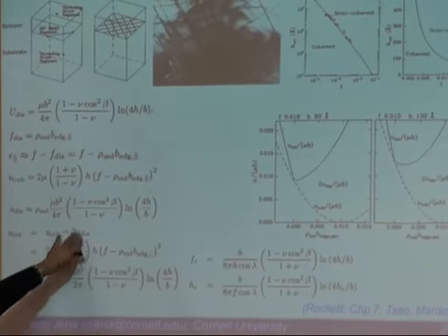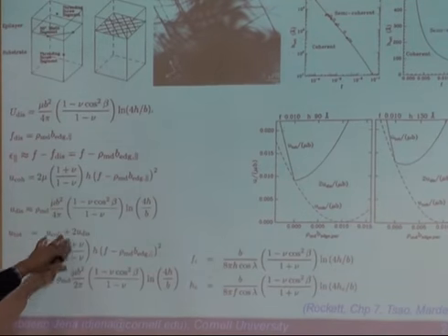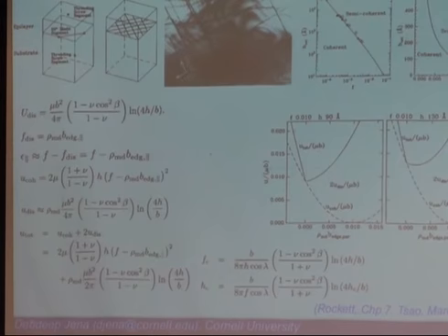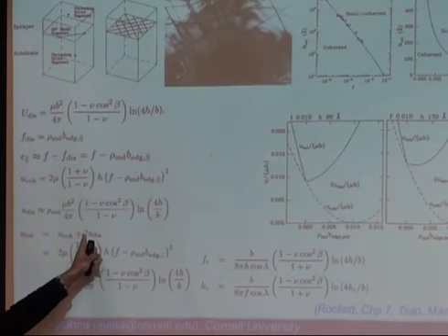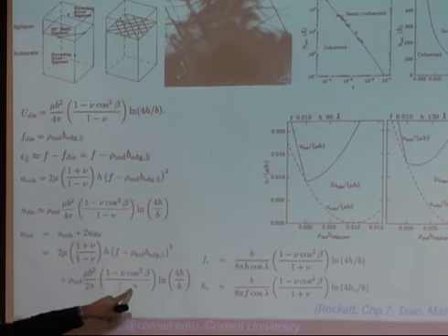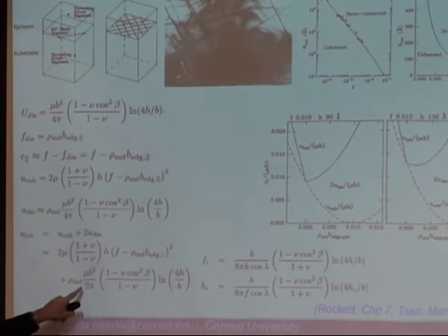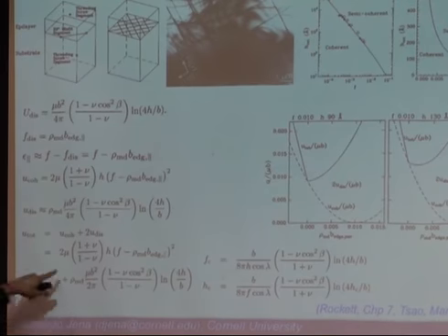Okay, let me just say, there are twos, and all these one can explain very clearly. The two comes about because the picture we're looking at now is if it had, for example, a dislocation in this direction and a dislocation in that direction, x and y. So there's a spacing along x, there's a spacing along y, right? So you form these dislocations, so there are two axes along which dislocations are formed. Just like we're summing it for epsilon along x, epsilon along y. Same thing here. You sum the whole thing over, and what you get in the end is total energy as a function of the dislocation spacing or density of dislocation, and obviously the height, h.